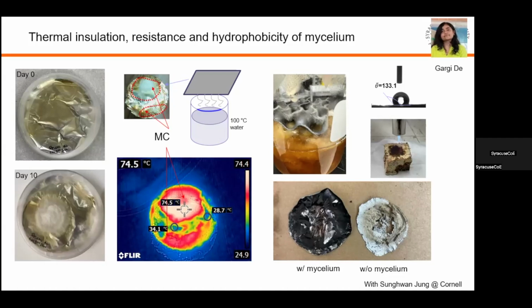So we coat the metal with mycelium, and we put this substrate on top of boiling water, 100 Celsius degree. Then we use the thermal camera so we can visualize the temperature distribution on the surface. You see, for the region coated by mycelium, because this mycelium is very thin, once you use a thermal camera, it's actually recording the temperature still on the metal surface, not the mycelium, because this is very thin.